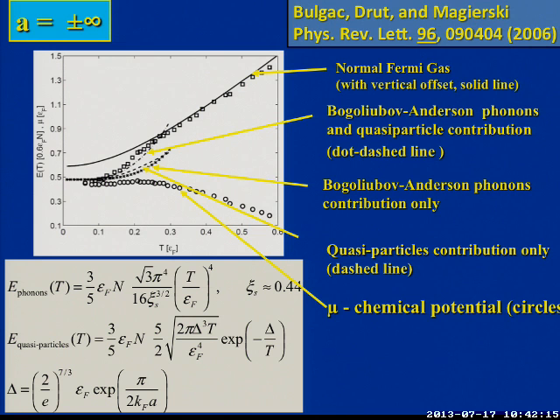We couldn't go lower than this temperature, which is a little bit less than 0.1 Fermi energy. You remember that the scale of the problem is given by the Fermi energy, or the density. That's the only scale in the problem. So something happens here. At that time, we identified this as the critical temperature, which wasn't the right thing. And I'll explain why.